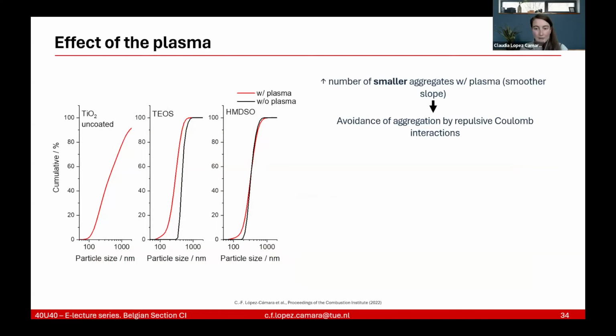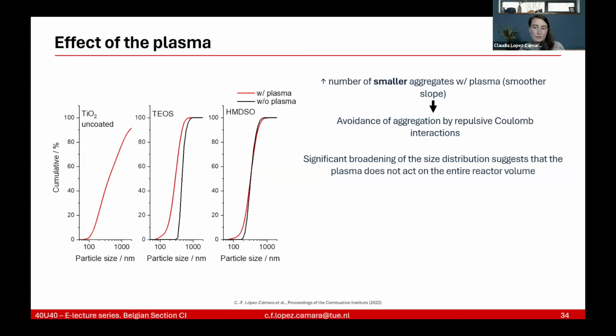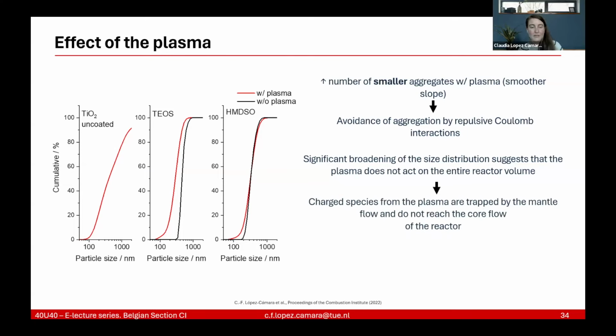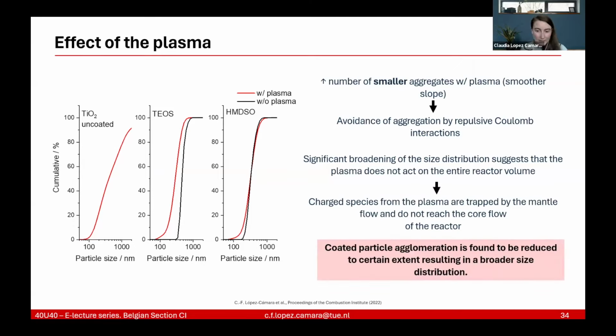However, there is a significant broadening of the distribution, which suggests that the plasma does not act in the entire reactor volume, which means basically that the charged species from the plasma are trapped in the mantle flow, so they are just affecting the outer part of the flow and do not reach the core of the flow of the reactor. That means that not all of the nanoparticles are seeing the plasma, and therefore the effect of the plasma is not as much as it could be. But in any case, coated particle agglomeration is found to be reduced to a certain extent. It could perhaps be reduced even more with other approaches, but it was already reduced a bit, resulting in a broader size distribution. So we know that TEOS works, we know that plasma works, so let's investigate a little bit more about the nuclei. Let's change the core to something a little bit more challenging or interesting, and let's see what happens.